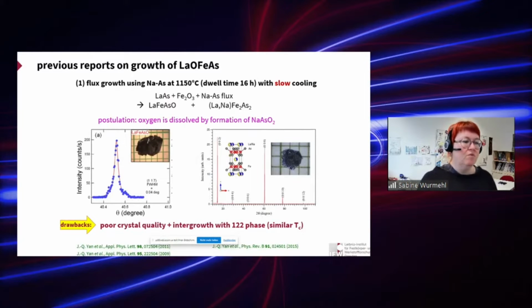One report was on flux growth using sodium arsenide with slow cooling, and the authors suggested an intermediate formation of sodium arsenic dioxide, which allows the dissolution of the oxygen and therefore the formation of the 1111 material. The problem is that the crystal quality, shown here by the full width half maximum, is not very good and not comparable to the other iron-based superconductors, and they were also intergrown with a parasitic 122 phase with a very similar TC, shown here, containing both lanthanum and sodium, iron-2, arsenic-2. This was, of course, also hindering their in-depth investigations.